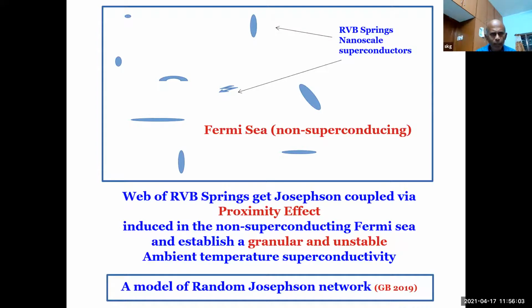the message is that a web of RVB springs gets Josephson coupled via proximity effect. This is again a well-known phenomenon that people have done beautiful experiments. You take a piece of niobium, another piece of niobium, put gold in between. There is the so-called anomalous proximity effect, more than what theory predicts, through gold and many monovalent metals. So in other words, gold is longing to become a superconductor because it's one of its instabilities. So given a chance, it nurtures it and propagates it to the other end. So there are anomalous proximity effects with respect to gold and silver.